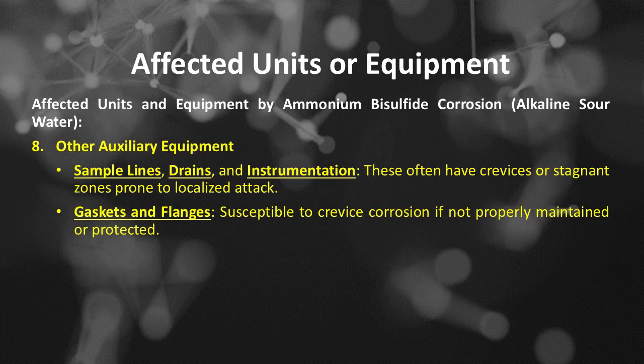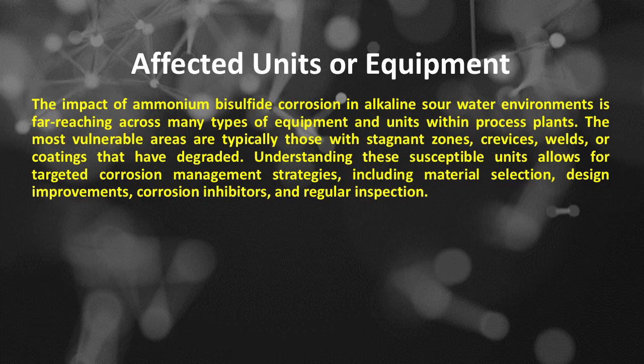These often have crevices or stagnant zones prone to localized attack. Gaskets and flanges are susceptible to crevice corrosion if not properly maintained or protected. The impact of ammonium bisulfide corrosion in alkaline sour water environments is far-reaching across many types of equipment and units within process plants. The most vulnerable areas are typically those with stagnant zones, crevices, welds, or coatings that have degraded. Understanding these susceptible units allows for targeted corrosion management strategies, including material selection, design improvements, corrosion inhibitors, and regular inspection.